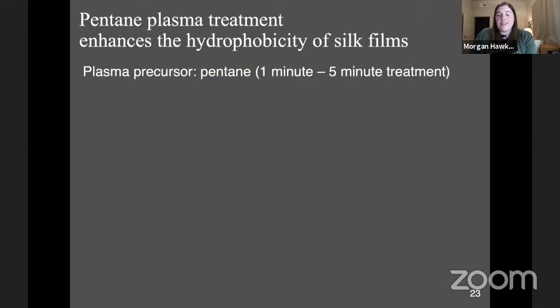One of my students has developed a novel plasma treatment method using pentane, a hydrocarbon precursor. And in her initial experiment, she's varied the time the silk materials are exposed to the plasma. So from anywhere from 1 to 5 minutes of exposing the silk film to the pentane plasma.